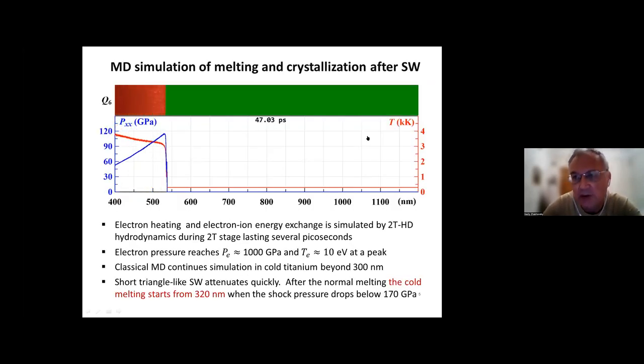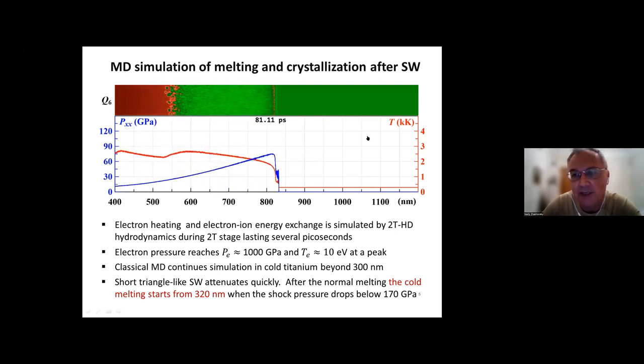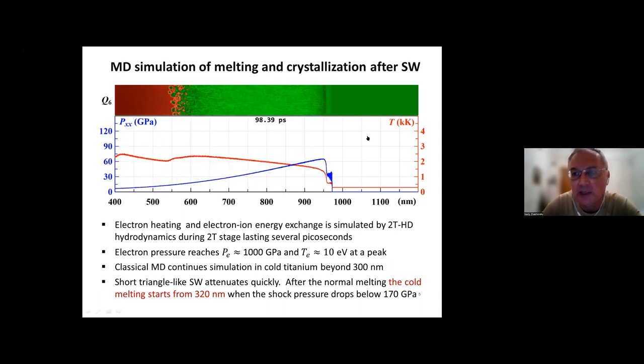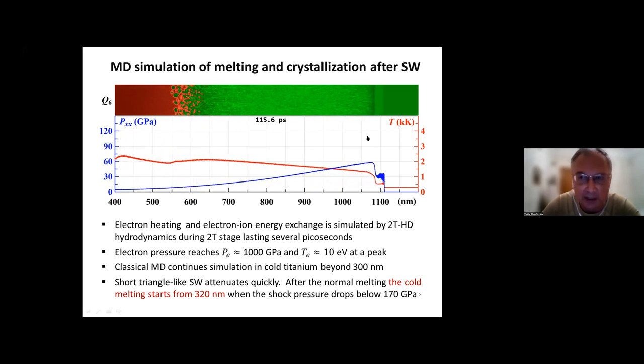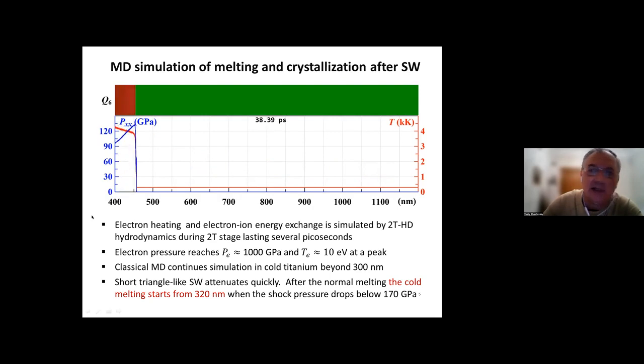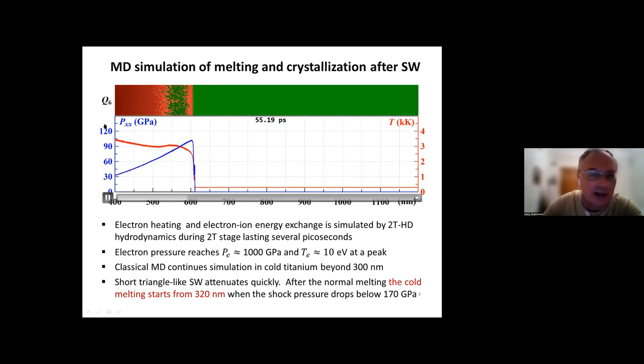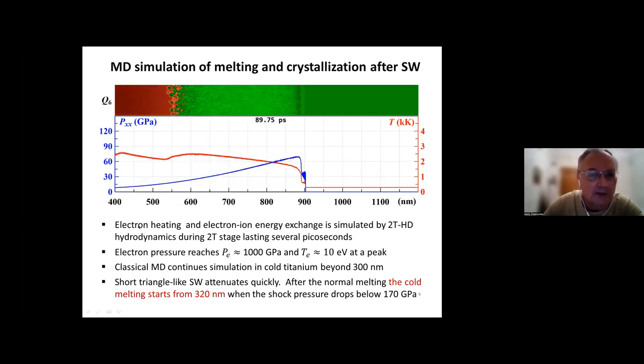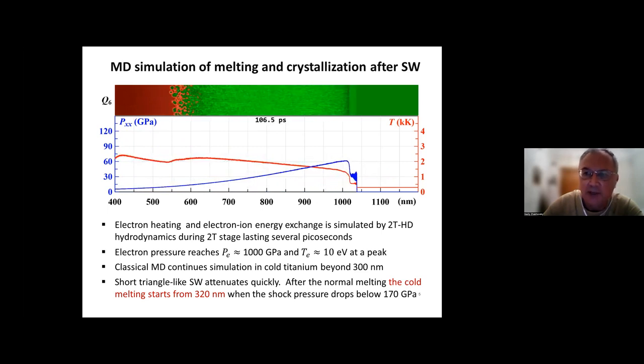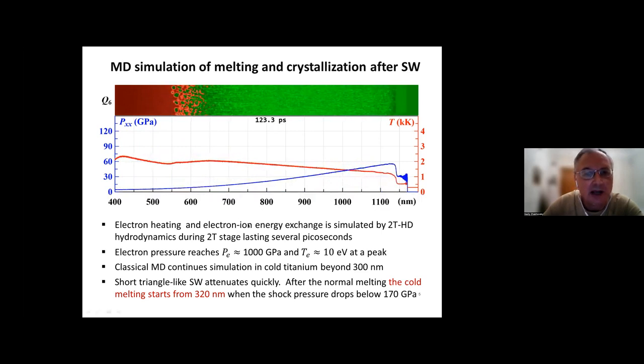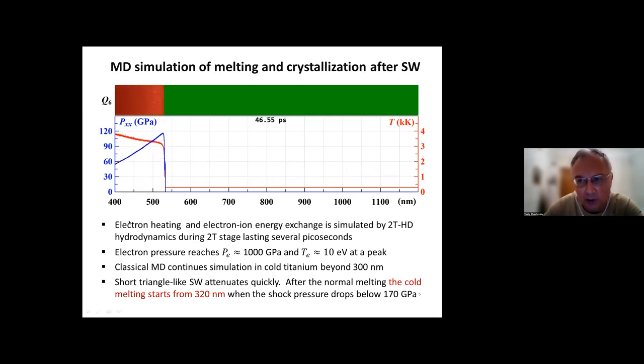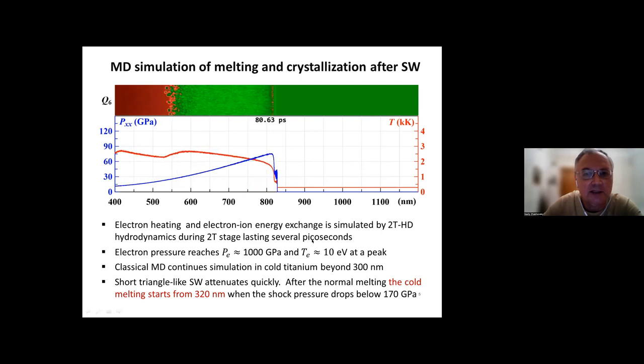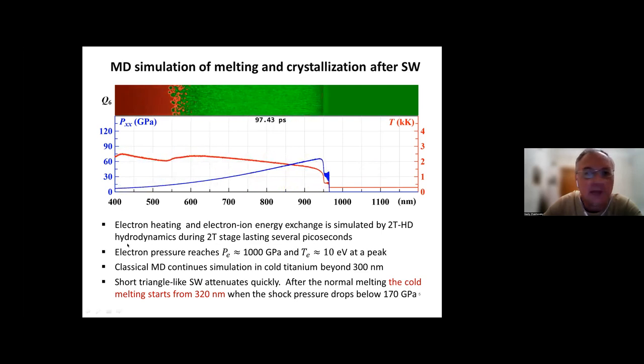Okay, because I have done molecular dynamics simulation all my life, in this work I focused only on MD results, and they of course show the basic physical mechanism which we observe. However, classical MD cannot be applied from the beginning of the simulation because the laser pulse hits first the electron subsystem, not the ions, and during this non-equilibrium stage we have high temperature electrons and low temperature ions. Electron heating and electron-ion energy exchange were simulated by two-temperature hydrodynamic codes with a coupling term responsible for energy exchange. This stage lasts several picoseconds, and then we may apply molecular dynamics.